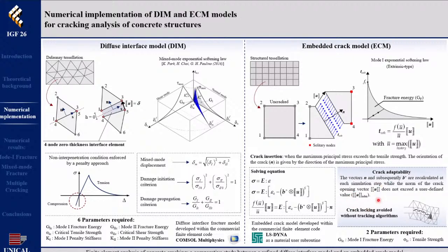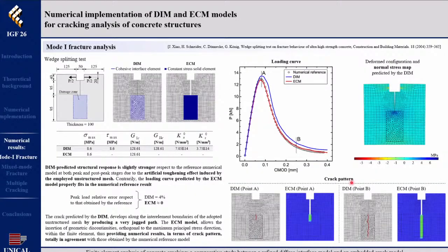This is possible thanks to the novel strategy employed in the ECM model based on a crack adaptability approach, according to which the principal stress direction is recomputed at each step of the simulation until a threshold value of the crack mouth opening displacement is reached. In this way, the brutal crack locking phenomena that is very frequent in the fracture simulation performed by intra-element approaches are avoided. Yeah, so you can practically say that this model also is quite consuming in terms of computation, can be interesting for this aspect or feature.